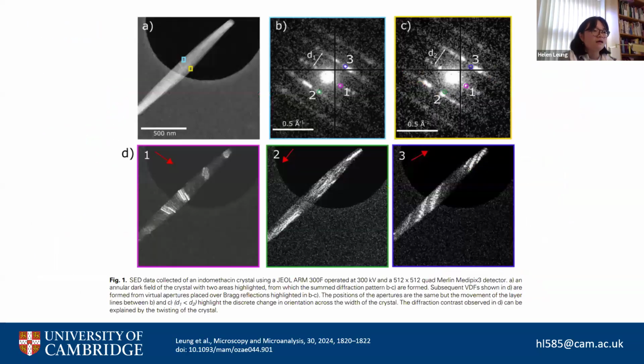Okay, and we then applied some 4D STEM to these crystals. What was difficult before is, if you can imagine, we didn't know the crystal structure before. We didn't know the form of our polymorph before. So just applying 4D STEM to it without a CIF file, without any understanding of what unit cell parameters we were looking at, was very difficult, essentially. And so I don't have time to go into this here, but there is a bit of work that you can follow the link to on the bottom of this slide if you want, and read a bit more about when we applied 4D STEM to this.